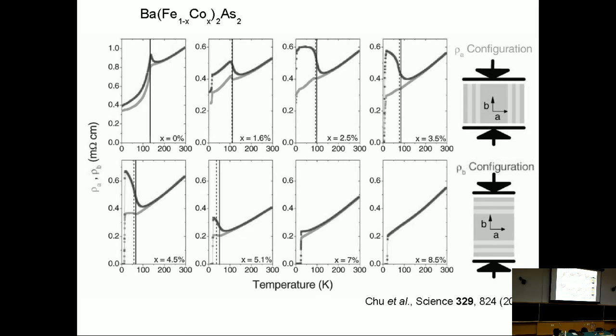So in principle, you have isotropic conductivity in the tetragonal plane at high temperatures, and you still have isotropic conductivity below the magnetic ordering temperature, because you have this equal population of domains. However, you can detwin the sample. You can increase the population of a specific domain at the expense of the other by applying strain. And when that's done, the resistivity curve can be measured along the strain direction, or perpendicular to the strain direction.